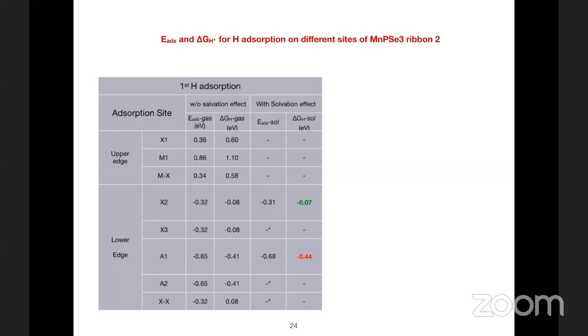I'll show you. I have 4 different compounds in 2 different structures, so there are 8 nanoribbons and many different possible sites on each of these. I won't explain all the details of what we see, but I'll try to convey the essential picture that we have found. Here you see adsorption of hydrogen on what we called ribbon 2 for MnPSe3, indicated in green color. The X2 site at the lower edge has a delta G which is very close to 0. On the other hand, there is another site A1 close to the central phosphorus atom, where the delta G value is large and negative. Our understanding is that when the hydrogen concentration is low, they are far apart, so X2 sites would be acting as the catalytically active sites.